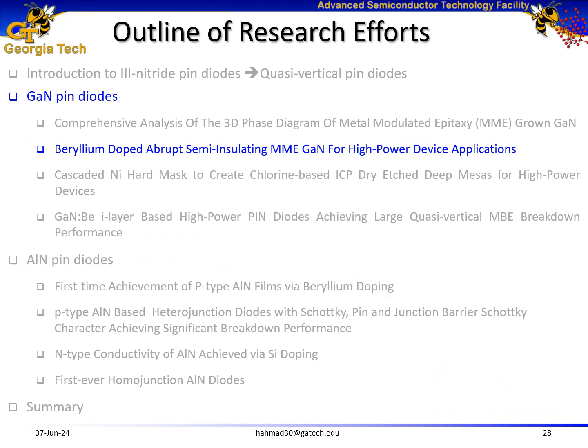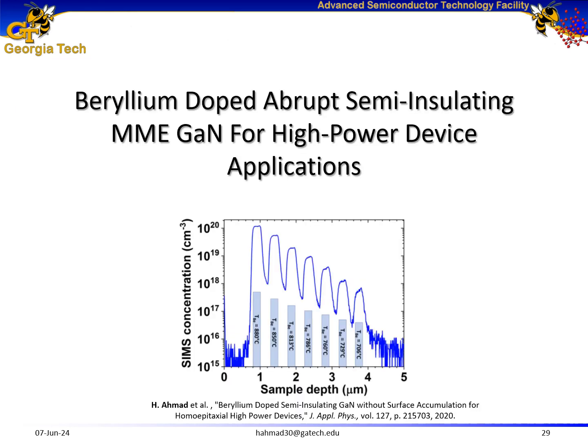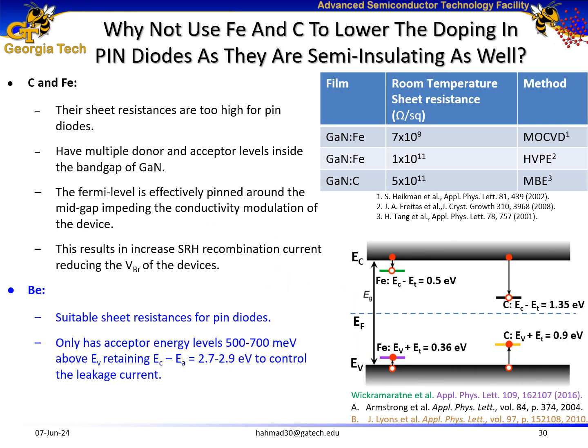So next I wanted to focus on the I layer of pin diodes. I wanted to reduce the background doping concentration to achieve higher breakdown performance for pin diodes. In this regard, I performed a study on beryllium-doped abrupt semi-insulating MME gallium nitride for high-power device applications. Now the first question arises, iron and carbon also results in semi-insulating films. So why can we not use iron and carbon for the I layers and pin diodes?